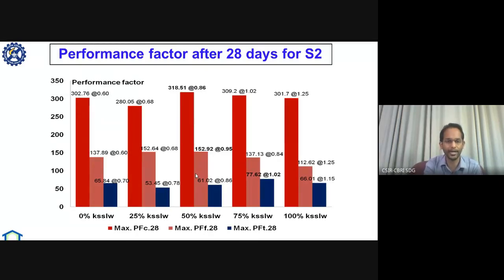And for S2, that is for 800 kg per meter cube, when you see the IS code that I have mentioned already, IS 2185 part 4, you will see that the standard value given is 315. And here we have got 318 at a percentage replacement level of 50%. So we have concluded that we can replace 50% of sand with slurry.